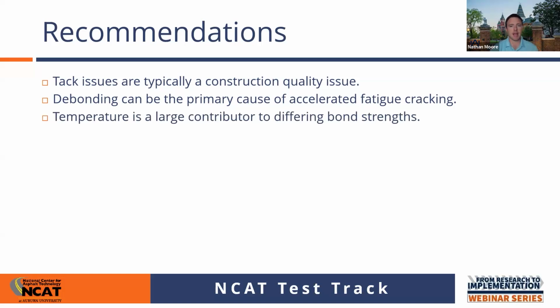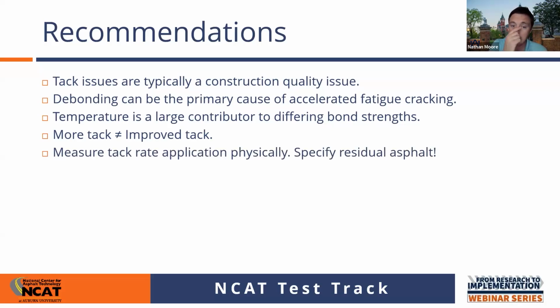Temperature is going to be a big factor in getting different bond strengths, and so comparing bond strengths across different temperatures and, for that matter, different loading rates is a dangerous task. You just need to make sure you understand the differences, and with higher temperatures, you're going to have much less shear resistance. There is a break-even point, where if some is good, more is better, but too much is a bad thing. If you have too much tack, there is a break-even point. So more tack does not necessarily improve bond strength.